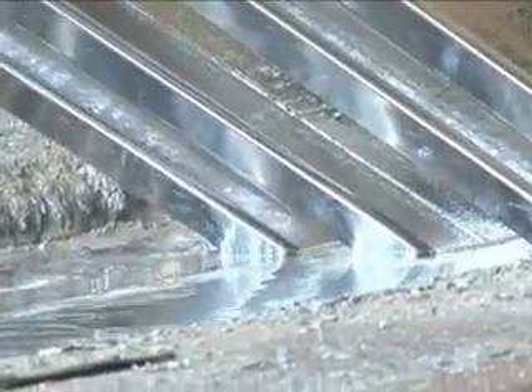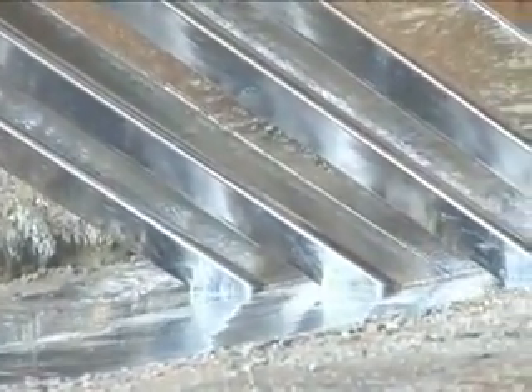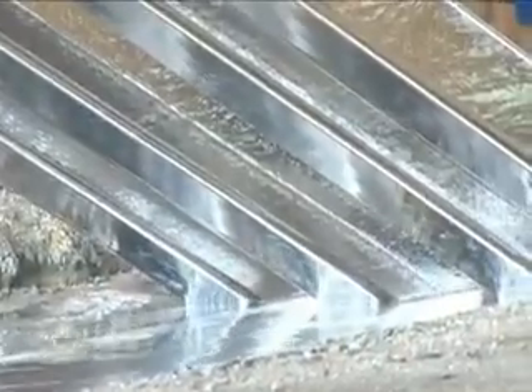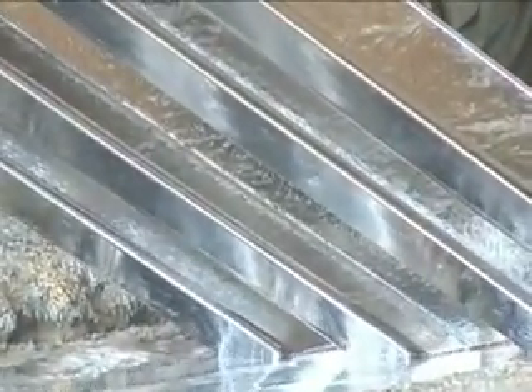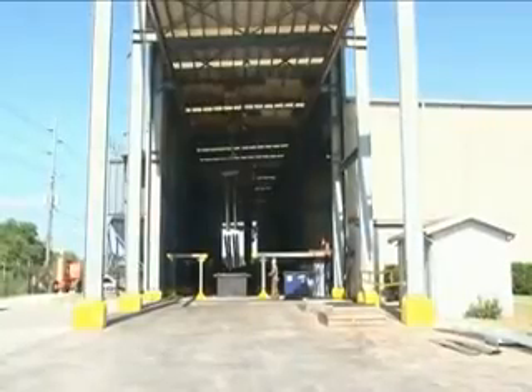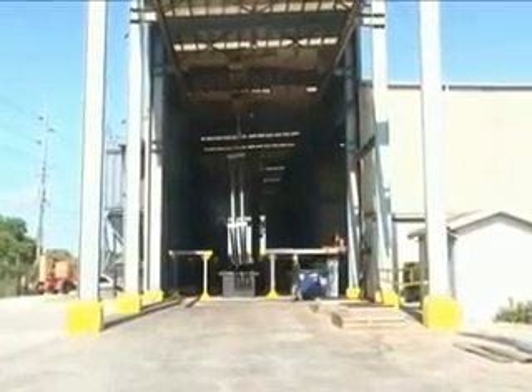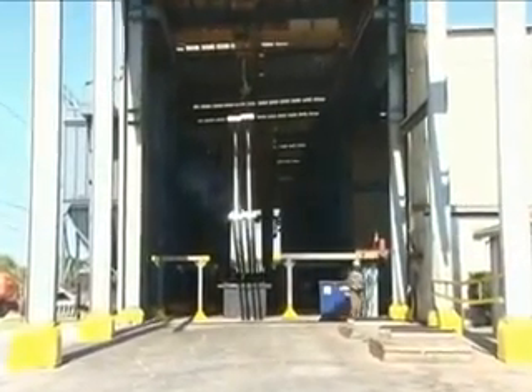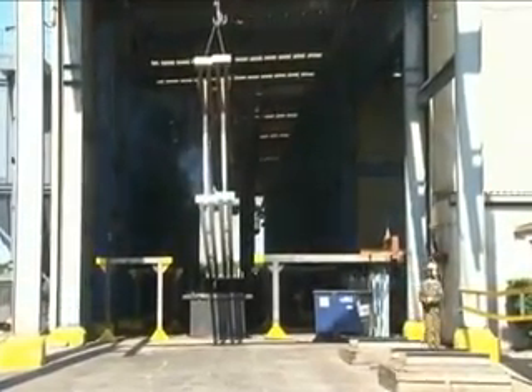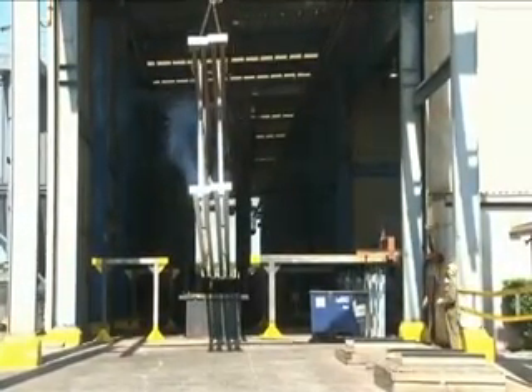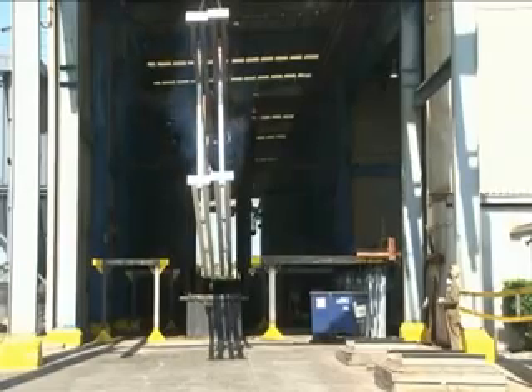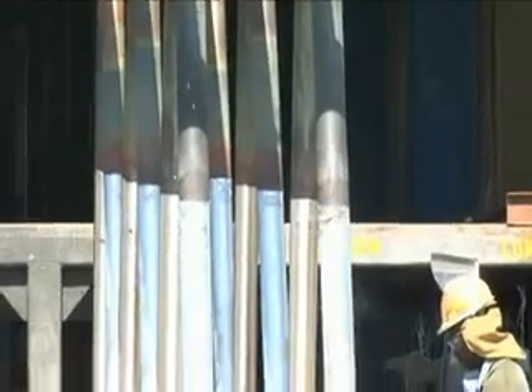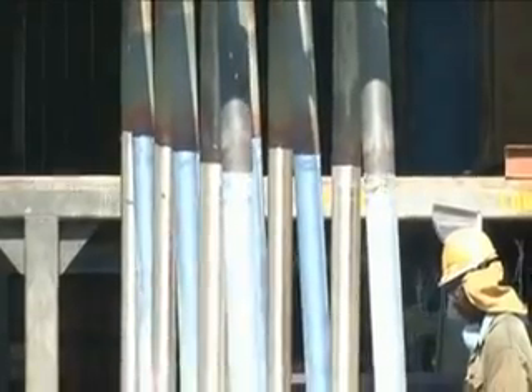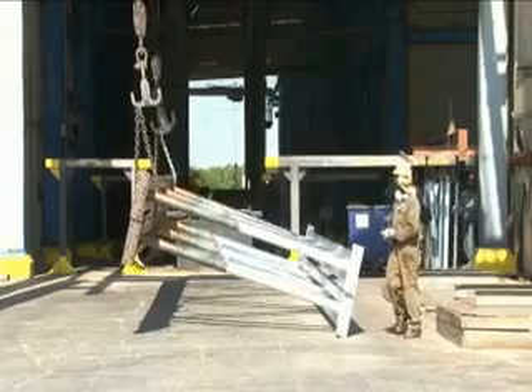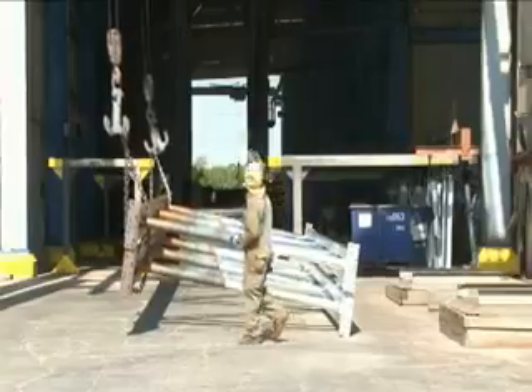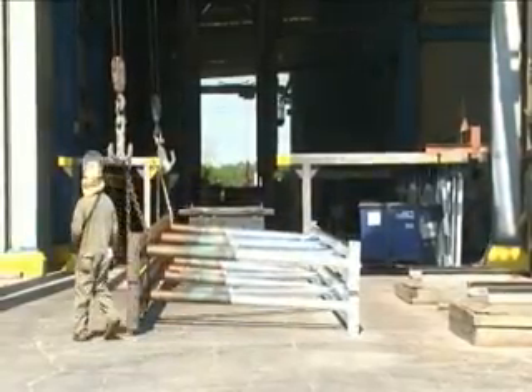This will be the first of the 2 dips. It comes out slow so that the zinc can drain out and also drain off. And that's the reason why everything's extracted at a very slow rate. Once the trusses are raised out of the 840 degree zinc coating tank, they're then wheeled out front for cooling down to 790 degrees. That's the temperature that zinc solidifies. Zinc solidifies at 790. So it's already cool enough that the zinc is solidified, and you can lay it right down on the concrete and it doesn't affect the coating.